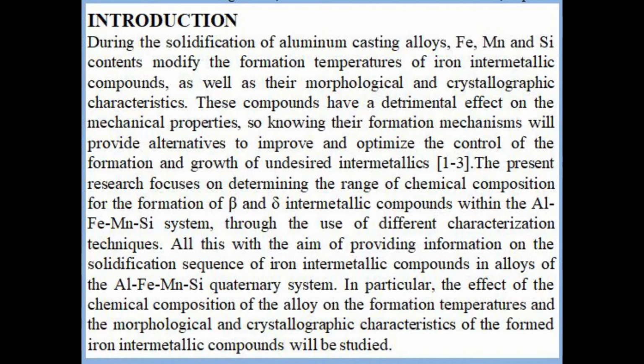During the solidification of aluminum casting alloys, iron, manganese, and silicon contents modify the formation temperatures of iron intermetallic compounds, as well as their morphological and crystallographical characteristics. These compounds have detrimental effect on mechanical properties, so knowing their formation mechanisms will provide alternatives to improve and optimize the control of formation and growth of undesired intermetallics.